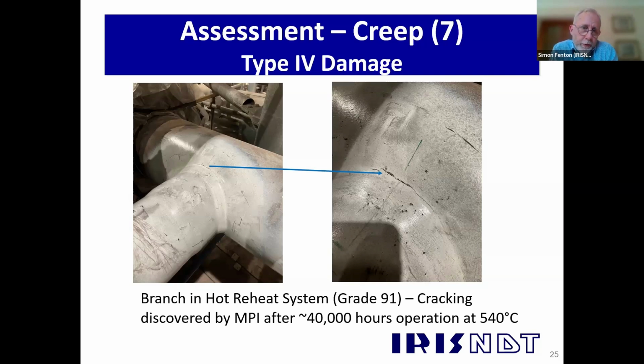So that's occurred after, again, about 40,000 hours of operation at about 540 degrees C. The material there is grade 91, P91. So this is a modified 9 chrome steel. And it's a particular steel that if you get the heat treatment wrong, you can suffer premature creep damage. So we're always quite wary of this material. Certainly use a lot of replication, a lot of NDT on circuits that are made up using that material.